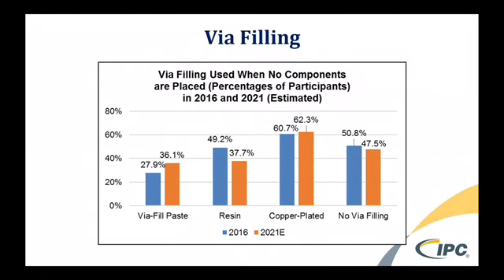Now, with blind vias comes the need: do we have to fill these vias? And again, it's going to depend a lot on OEM preference. But up till now, at least for this current level of technology, at our board level, we do have a definite good cadre of techniques used to fill these vias, whether they be via filling paste, which is a ceramic filled epoxy that can be screened into vias and cured, and then later planarized and plated. We also see a big growth in the area of copper via filling, or what we call super fill. And again, this is using plating techniques or potentially even copper sintering paste to plate the vias completely full. And of course, along with that goes the need for proper plating processes, equipment, agitation frames, and controls.